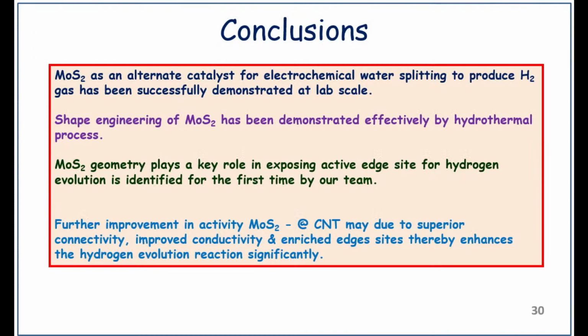So in conclusion, first, MoS2 is an alternate material for electrochemical hydrogen production. Shape engineering affects the surface morphology beyond surface area. So MoS2 geometry plays an important role in exposing active sites for hydrogen generation. Further improvement of conductivity can be done by decorating MoS2 over the CNT, so that we can go for further enhancement of the activity in the single cell analysis. So in continuation,